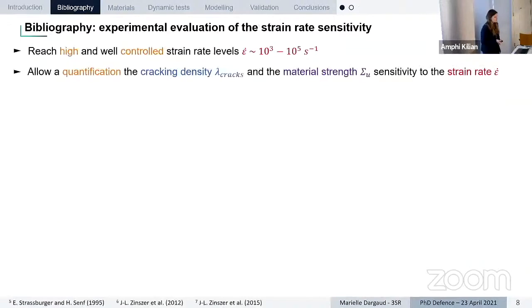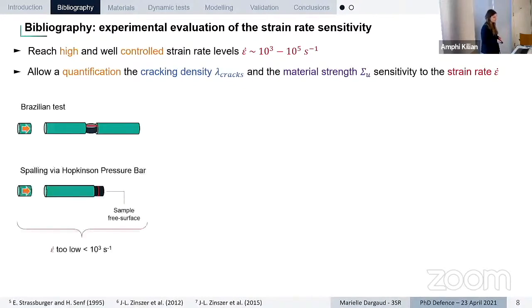So when we look at the literature, we have some experimental setup to characterize the tensile behavior of the ceramic, because here we are going only to focus on the tensile behavior, which causes the fragmentation of the ceramic. So the goal is, with this experiment setup, to reach high strain rate, with a controlled strain rate, and to be able to reach some quantifications such as the cracking density and the material strength. The first type of experiment are Brazilian tests or Hopkinson pressure bars, but they are very limited in terms of strain rates, level of strain rates that we can reach.